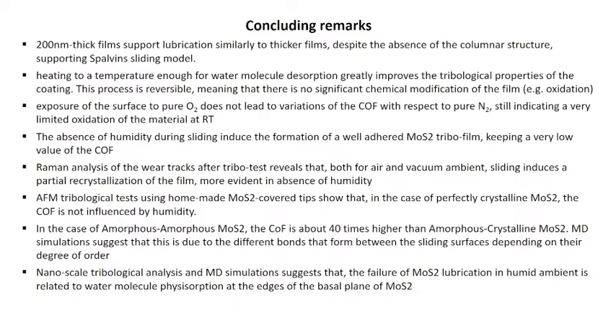By means of AFM, we were able to study in more detail the fundamental process that drives the phenomena on MoS2, and we found that in the case of the amorphous layer, the coefficient of friction is 40 times higher with respect to the crystalline case. This suggests that effectively the role of water physisorption is the most important one in the case of room temperature. And this result has been also supported by molecular dynamics simulation, even if the absolute values do not completely fit what we found in the experimental results.